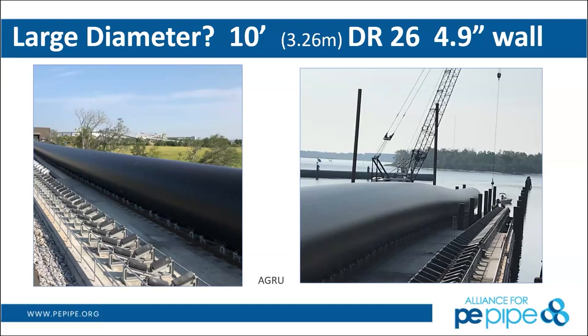The process is basically very simple. It's basically the same operation as making short pipes. We're just not cutting the pipe. We're actually extruding it into these long lengths. We're ensuring the wall thickness by using ultrasonics to measure the wall thickness during the production of the pipe, and then counting the footage of the pipe to make sure that it is made to the correct lengths. And then we're able to extrusion weld plates onto the pipe so that it can be buoyant and float in the water. And these pipes can be anywhere from 5 feet in diameter all the way up to 10.5 feet in diameter to be towed anywhere a job site has where it's near shore.